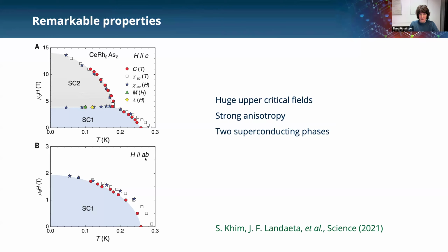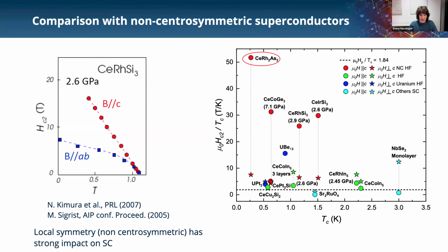For fields in the plane, the phase diagram looks more standard. As you see here, just one superconducting state, but still the upper critical field is very large, although it's much lower than along c, but it still strongly exceeds the Clogston-Chandrasekhar-Pauli limit. Okay, so this strong anisotropy with large critical fields along the z-axis is very well known for non-centrosymmetric superconductors. To show you an example, here's data for cerium rhodium silicon 3 at 2.6 GPa, where Tc is the largest in this material.